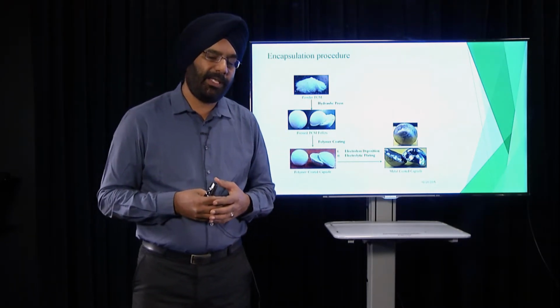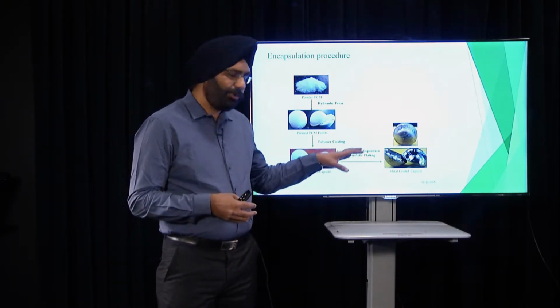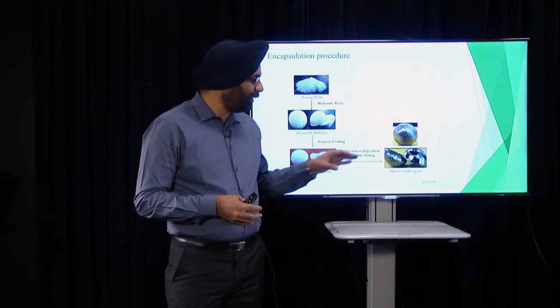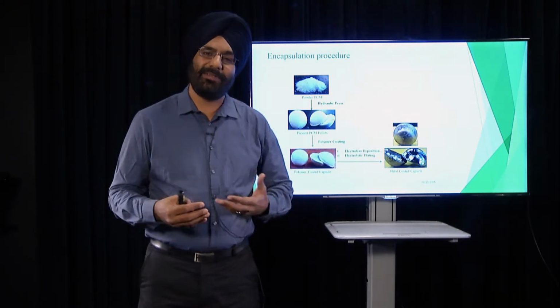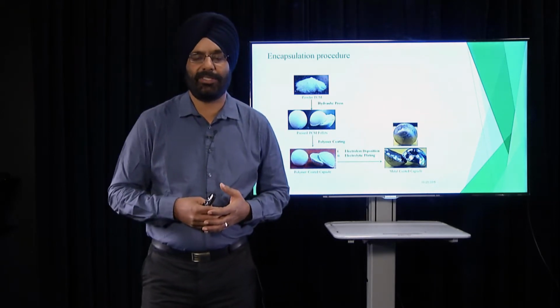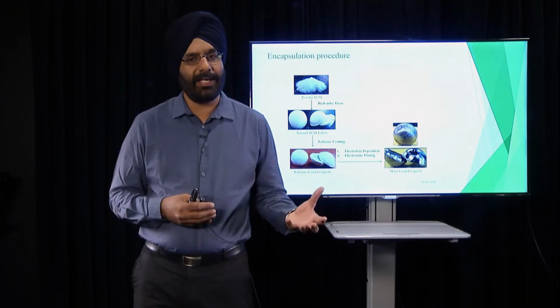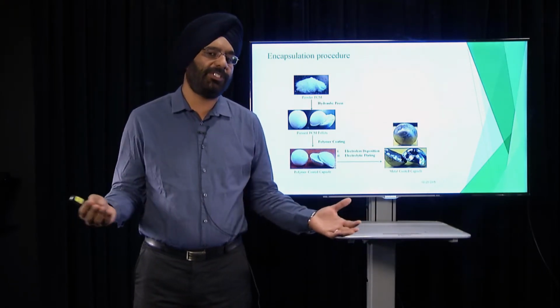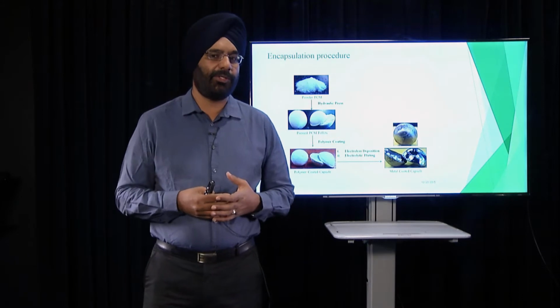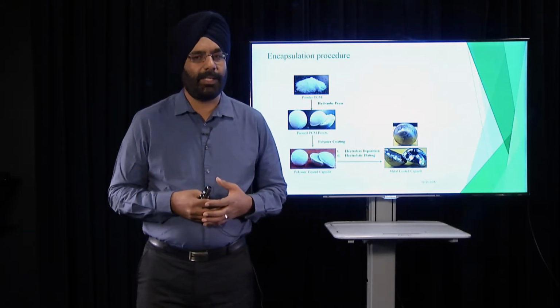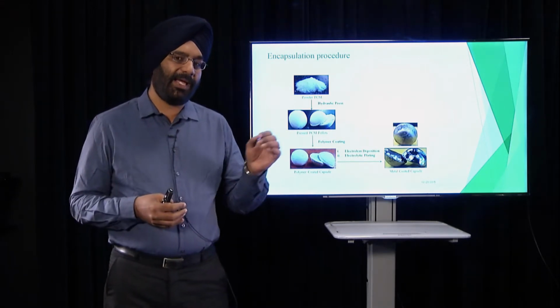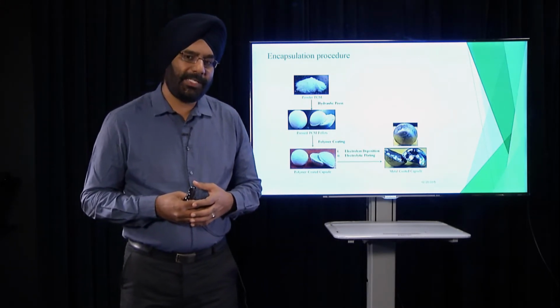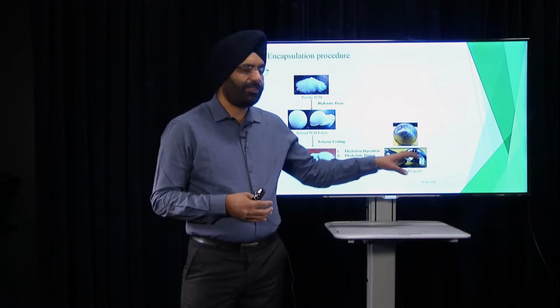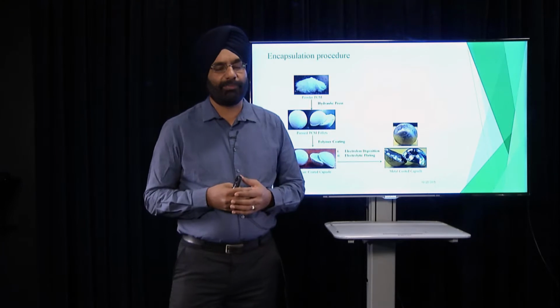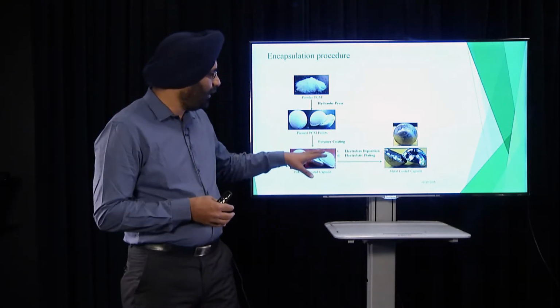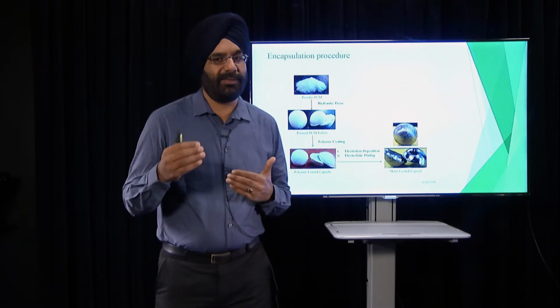There has to be some unique features in this metallization. But broadly, the techniques which we used, available in the market, are electroless deposition and electrolytic plating. What is electroless deposition? It's a simple redox chemistry reaction where you use a solution containing metal ions and then you reduce it with a reducing agent so that the metal ion gets converted into metal. When you do that reaction on a small molecular or ionic scale, you will have very small particles of metal deposited on the substrate, and that's the reason you get a very good coating of the metal. The issue with electroless deposition is you cannot build thickness.